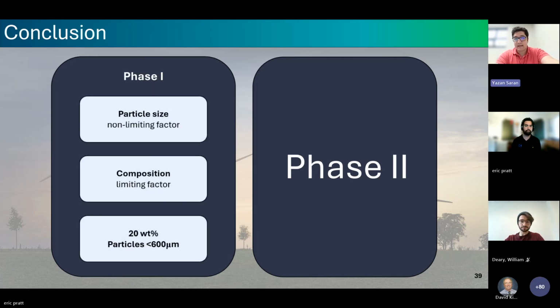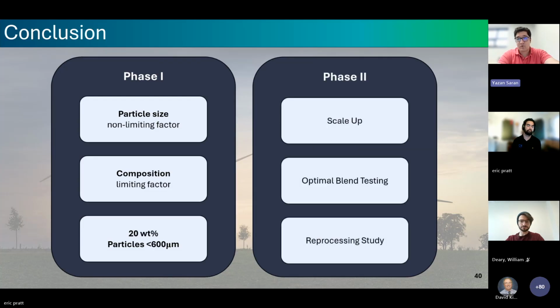Doing so, we concluded that particle size was a non-limiting factor, while the composition or weight percent of the cross-linked polyethylene in the polymer matrix was the governing factor when it came to the processability of our material. Therefore, we were able to move forward with a selection of 20 weight percent cross-linked polyethylene at all particle sizes under 600 microns.